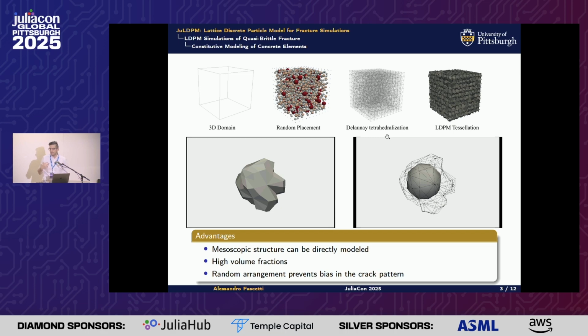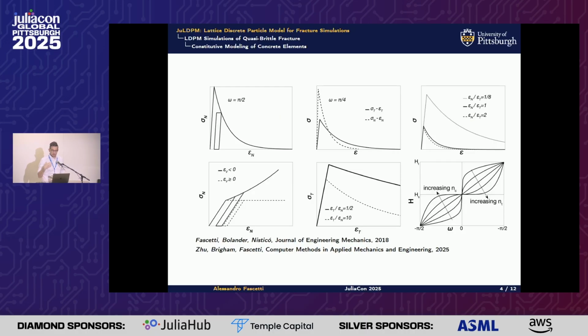The idea is that, especially for concrete, this is really a direct representation of the fracture itself, because the fracture is governed mostly by the tortuosity that's induced by the fact that the particles have different sizes and orientations. So you have this direct representation of these fine-scale features that provides a lot of advantages when simulating fracture. I'll give you just a couple of examples now.